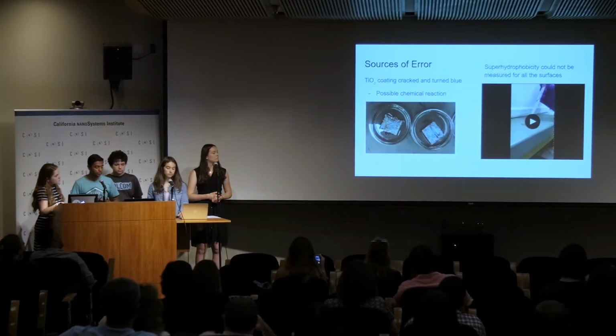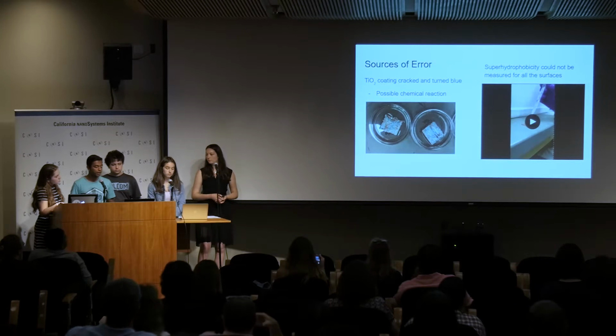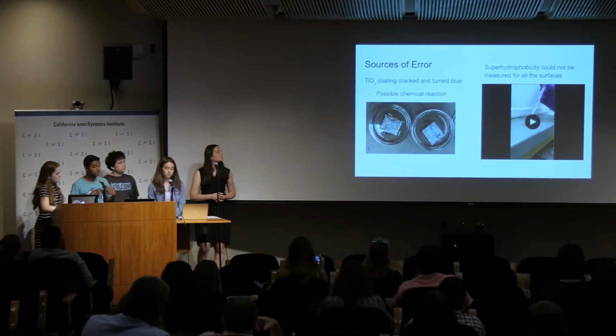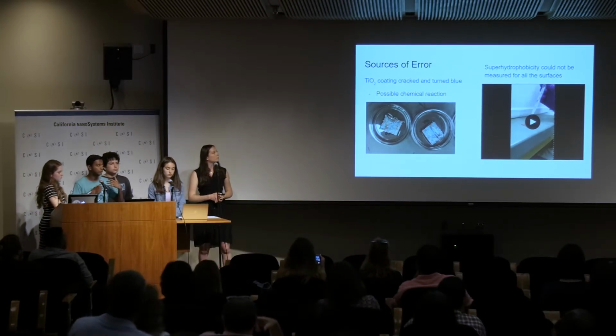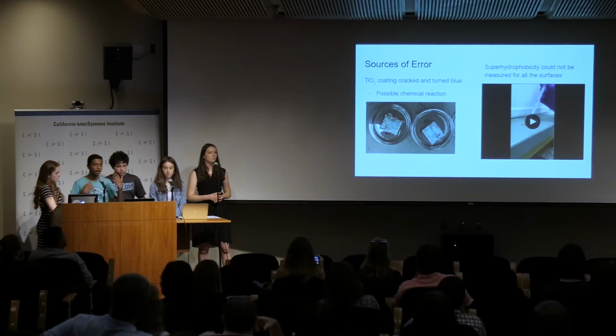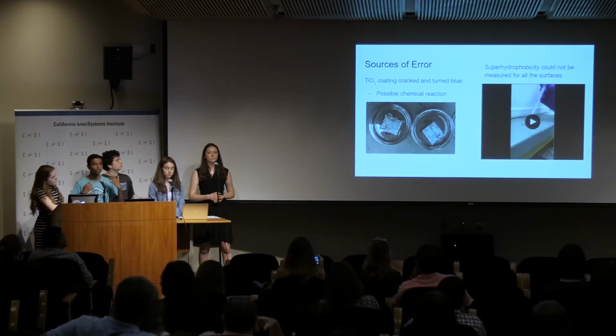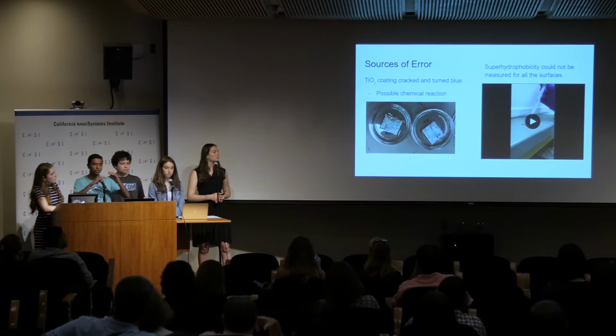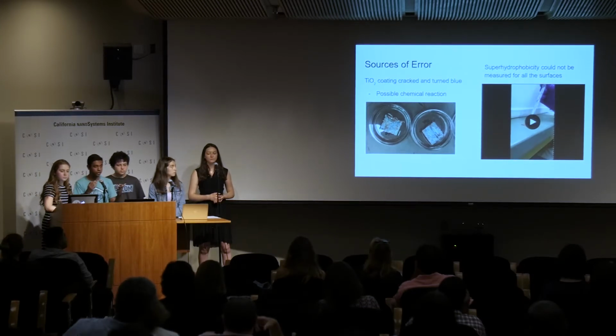However, we did have a couple of sources of error during our experiment, and the first one would be related to our TiO2, because our TiO2 on application and after it dried, it started cracking, which basically left holes for the solutions to go in and actually interact with the copper, thus corroding it.